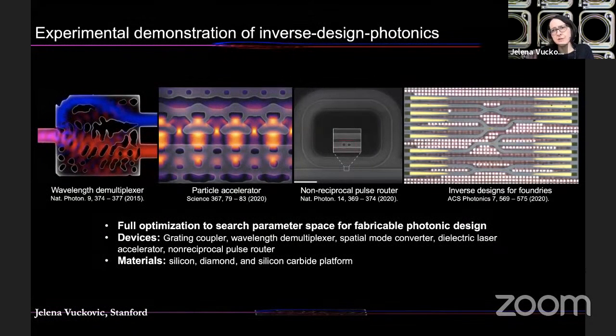So this is not the topic of this talk, but we've done a lot of work on a variety of other things. Apart from these wavelength splitting devices, we've also demonstrated one single stage of a laser-driven particle accelerator. We've accelerated electrons with something like 30 mega electron volt per meter gradient, and we're cascading these stages to build a mega electron volt accelerator. We've shown some non-reciprocal pulse routers, which are useful for ranging measurements. And we've also shown that this is fully compatible with foundry-based fabrication, as I'll show you in a moment.